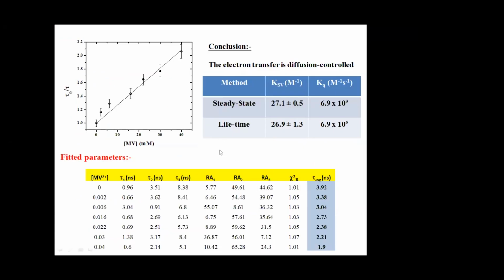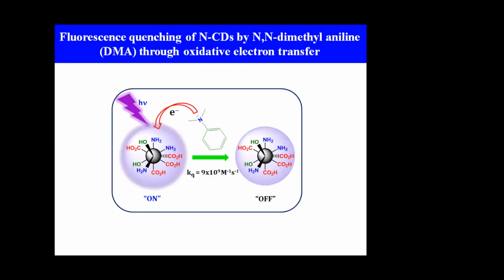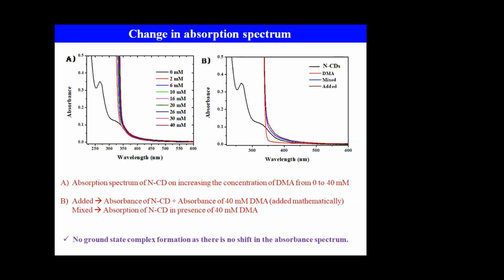Now it is also showing a multi-exponential fitting as usual with the carbon dot, multiple exponential. So we compared the KQ values, more or less they are similar, we don't see much differences. So here it can also work with dimethyl aniline. It can also work like an electron acceptor. So you have the advantage of using this material as electron donor as well as electron acceptor, which can have multiple bichromophoric - basically it's bichromophoric.